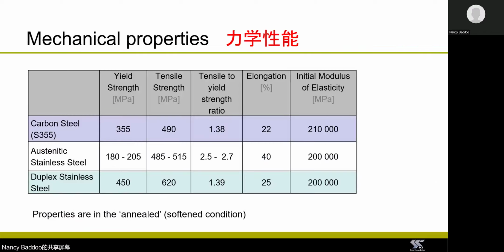Just to summarize things, I have a table here showing the mechanical properties and the strength used in design, the yield strength. You can see the austenitics have a yield strength around 200 megapascals, and the duplexes is more than twice, around 450 megapascals. Because of the strain hardening, the tensile strength is somewhat higher than you might expect, around 500 megapascals for austenitics and 600 for duplexes. So you get a sense for the effect of strain hardening when you look at the ratio of the tensile to yield strength.